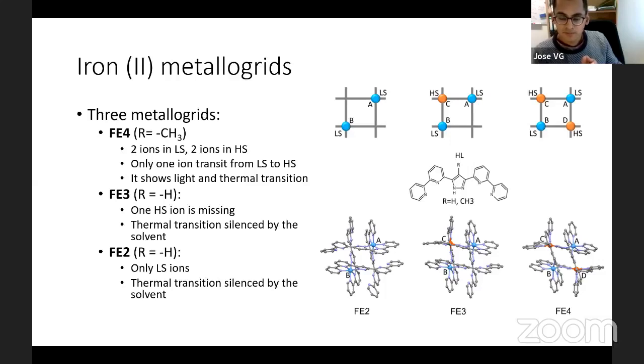So in this case, this material, the so-called iron 2 grid, is practically a dimer. It's a monometallic material, but arranged in a dimer configuration with 2 crystallographically independent metals. So when we photoexcite, we were expecting it to behave more like a monometallic material, which is quite interesting, as we will see. So we have the 3 systems: one totally connected, one connected only in an L shape, and one where the 2 low spin ions are not connected.